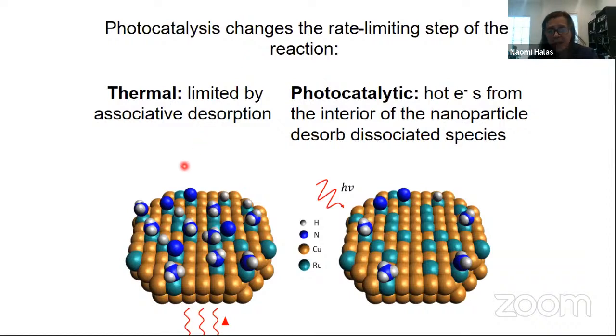A simple way to think about this is by cartoon. If we think about the conventional way that ammonia is decomposed, as I mentioned just a minute ago, it's limited by associative desorption. So you have ammonia sticking on the surface at all of the little ruthenium sites, and then we're breaking nitrogen-hydrogen bonds, but then we're left with nitrogen sitting on the surface, and it's just waiting, right? The energy needed to drive the reaction has to do with desorbing these nitrogens and getting them to form N2 and leave the surface. So it's sort of like a poisoned catalyst waiting. That's the rate limiting step.